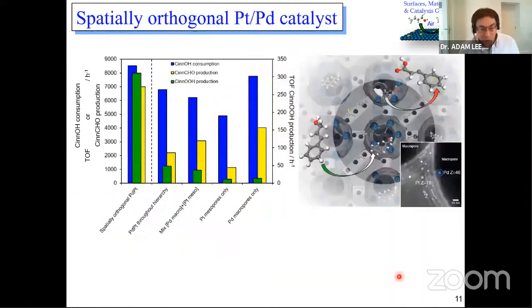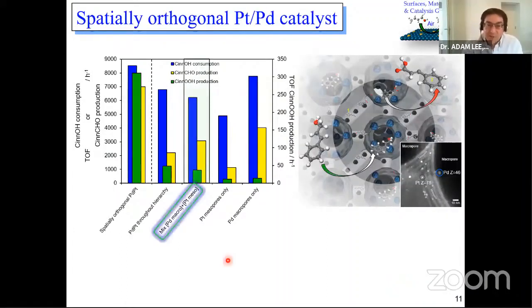So does the catalyst work? Well, I wouldn't be telling you about it if it didn't. So the first question, though, is how does it compare to, for example, a physical mixture? So if I make a conventional palladium and a conventional platinum catalyst and simply throw them separately into the same flask, we make a physical mixture, and we try this transformation of the alcohol to the aldehyde to the acid. What you find is that the catalysts are very good for the first step of the reaction. We're very good at reacting the alcohol, but we make very little of the final product of the cascade. So that's the acid here.